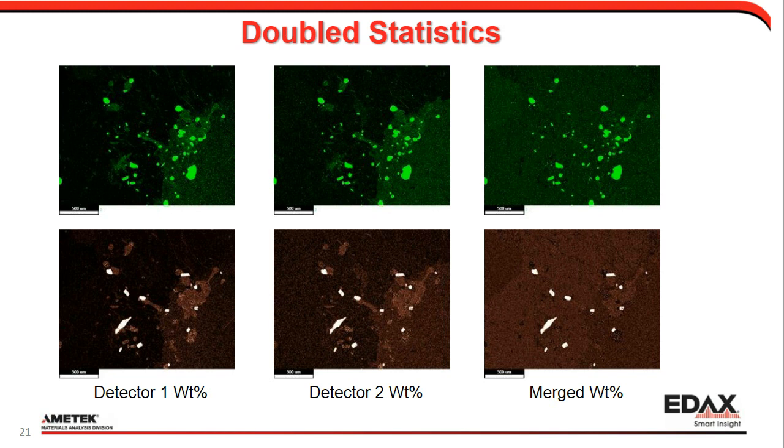The same thing for the zircon map we have down the bottom. We can see there is a slight contribution from the silicon, but not too much. We have more of a contribution from the iron inclusions. And when we then add the two together, add the spectra together, not the maps, the spectra, and do math on it, we can get rid of most of that iron, the strong iron inclusion and the silicon contribution. We can now see there's a bit of residual from the calcium iron that we could pull out by increasing the statistics, again, by simply counting for longer.